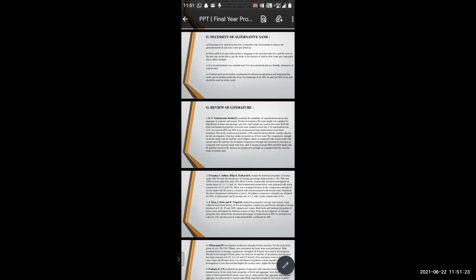The second one is Priyanka A. Jadhav and Dilip K. Kulkarni. Both studied the hardened properties of mortar made with manufactured sand, and mortar mixes with varying percentage replacement of 0%, 50% and 100% of river sand were used. The mortar mixtures were prepared with water cement ratios of 0.5 and 0.55.